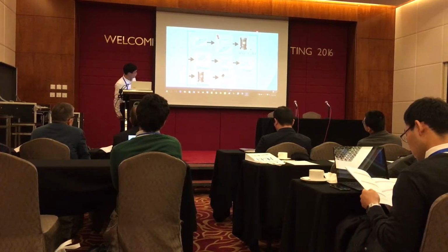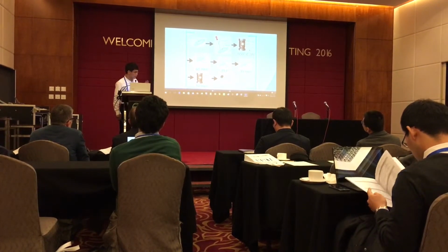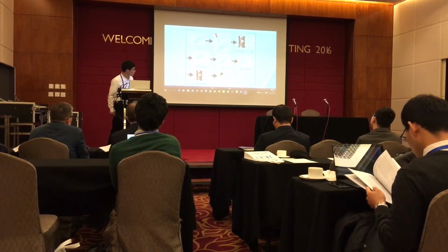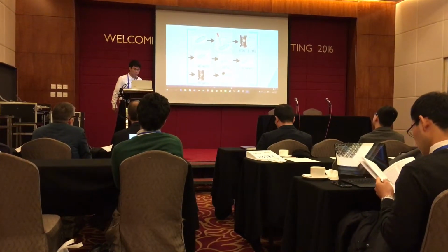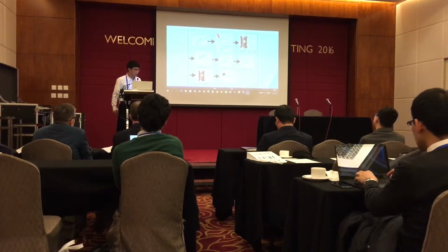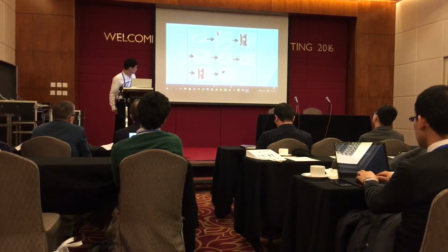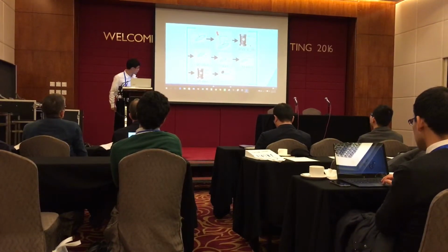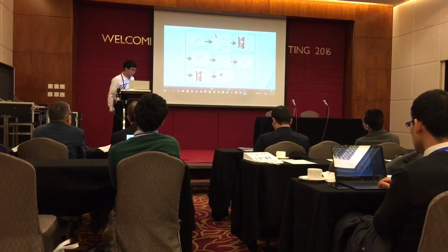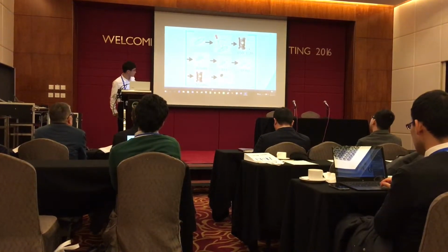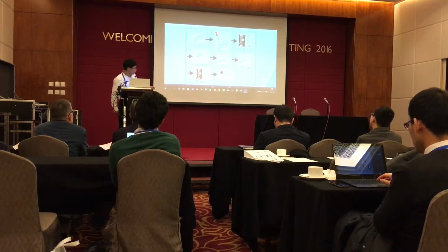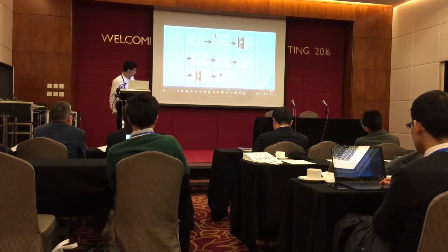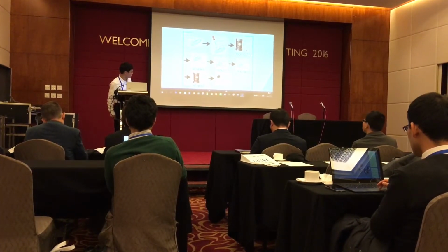We use hydrogen fluoride to remove the oxide on the substrate, then put it in the MBE chamber, thermal cleaning for 1 hour at 850 degrees Celsius. Pre-nitridation for 40 minutes. This process is optional. Indium droplet formation for 30 seconds, and nitridation for 30 minutes, annealing for 10 minutes. RHEED analysis is employed in every stage.